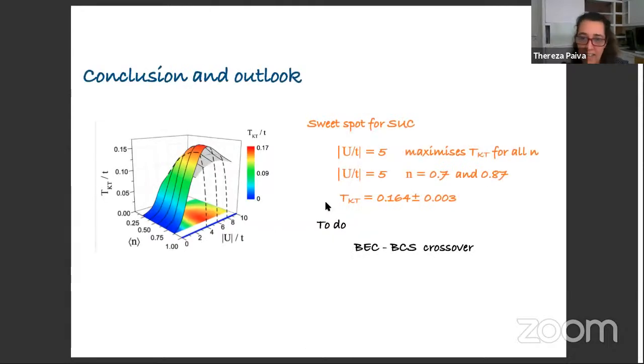So I guess I was really fast, but the conclusions I come to: there is a sweet spot for superconductivity in the attractive Hubbard model. This sweet spot is around U over t equals 5. This is where the Kosterlitz-Thouless temperature is maximum for all the densities. But if we can control the density in experiments, it's good to keep it in this range between 0.7 and 0.87. And this is the actual best estimate we have so far.